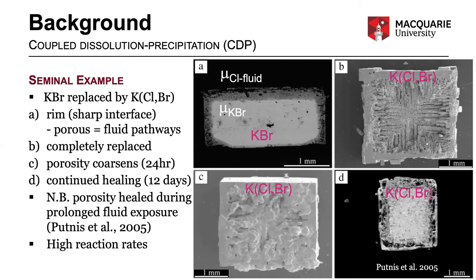So for background, for people that aren't too familiar with the process, in the classic experiments by Andrew Putnis, potassium bromide crystals were placed in a chlorine-rich fluid. In panel A, a rim develops that's porous. The porosity provides pathways into the core of the crystal. In panel B, the crystal has been completely replaced by coupled dissolution precipitation. After 24 hours, the porosity coarsens in panel C, and by panel D, the crystal starts to heal after 12 days. Note that with prolonged exposure to the fluid, the porosity that is integral to the coupled dissolution precipitation process can completely heal. They also found that the reaction rates are very high.